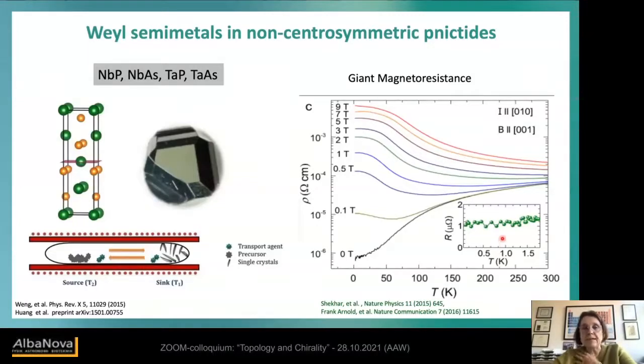The next experiment I told you was that this is the way we have grown the crystals, by chemical vapor transport. Therefore, we really could grow this very nice big crystal. But here you see these giant responses. So you see here the resistance versus temperature. And you see if we have no magnetic field, we have here wiggles. And these are not noise. These are quantum oscillations. It allows us to say exactly where the Fermi energy in our crystal is, so we know exactly how close in our crystals we are to the Weyl points.